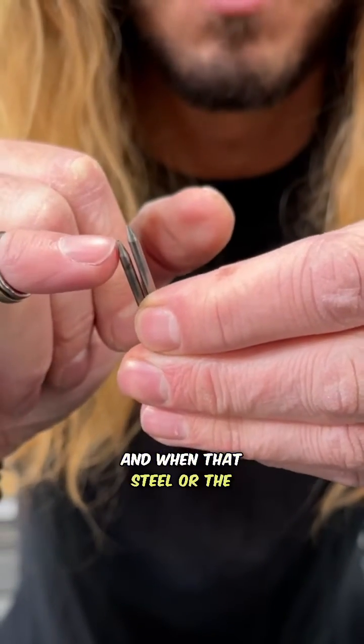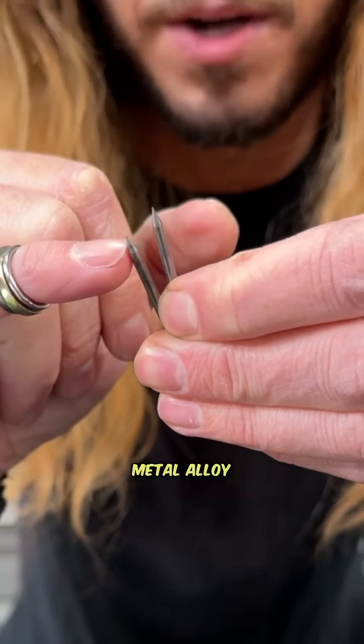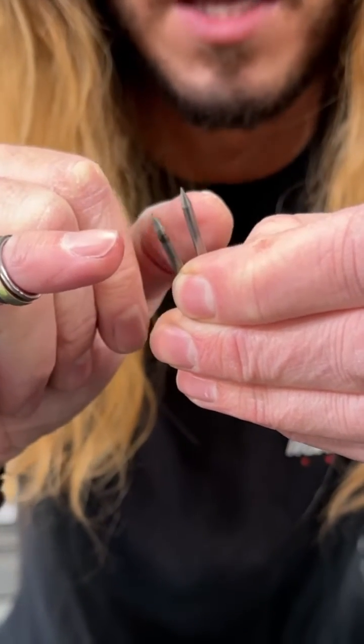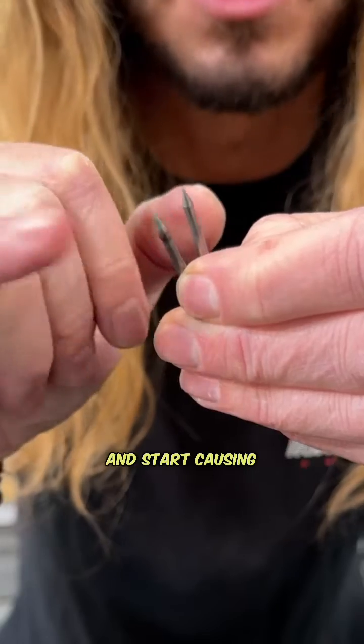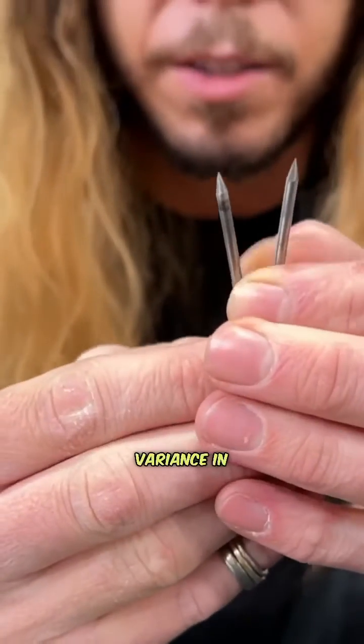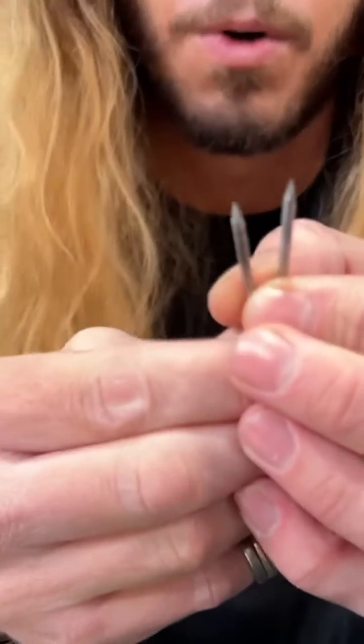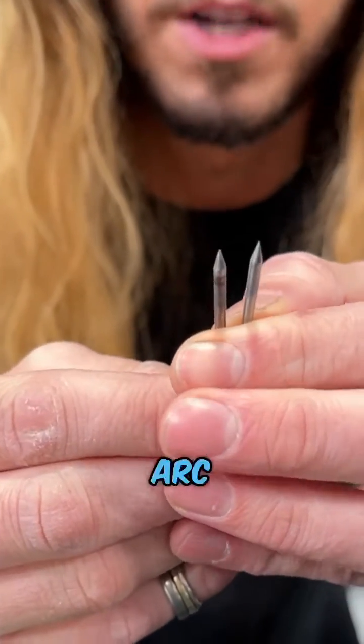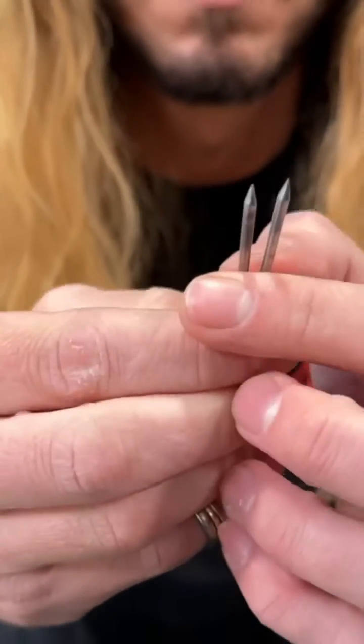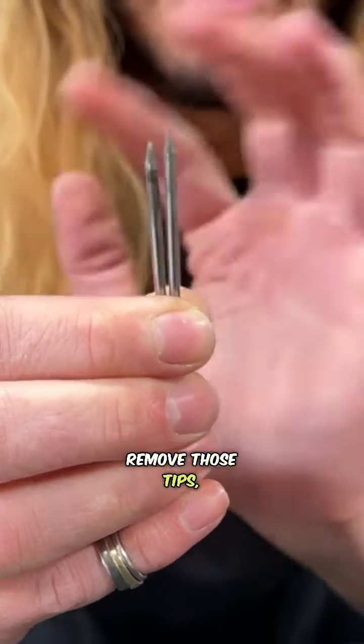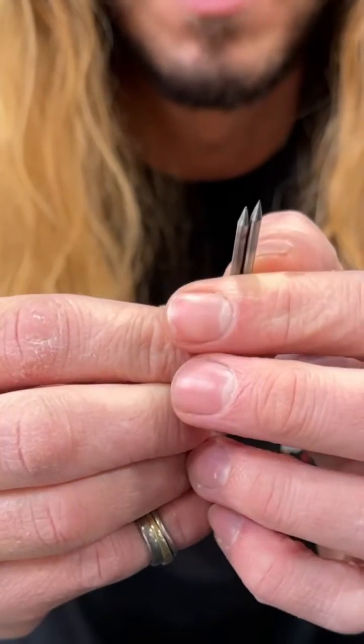When that steel or aluminum, any foreign metal alloyed into this tungsten tip, is going to melt, it starts causing a bunch of variance in the arc, causing the arc to flutter and swirl, and we're not going to be able to hold a true arc and deliver the amperage we need to the puddle. So remove those tips, throw them away, and get back and take control of your TIG welding.